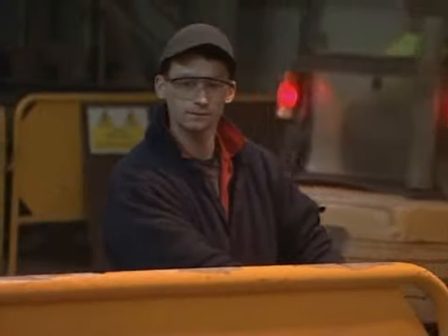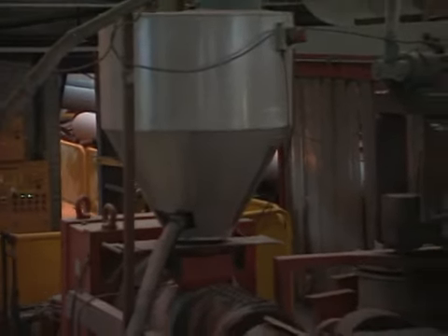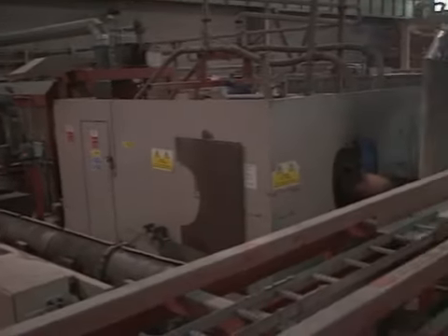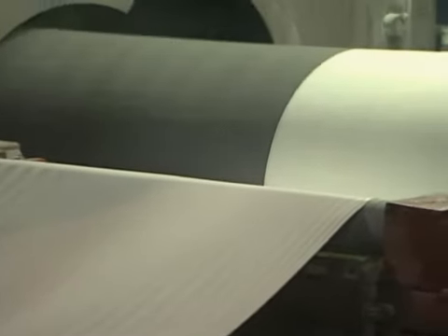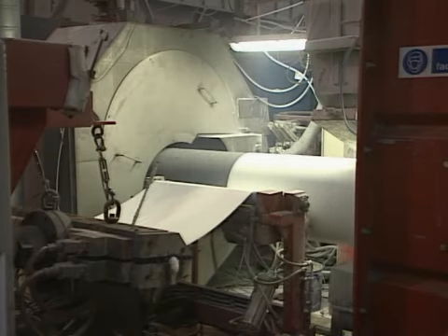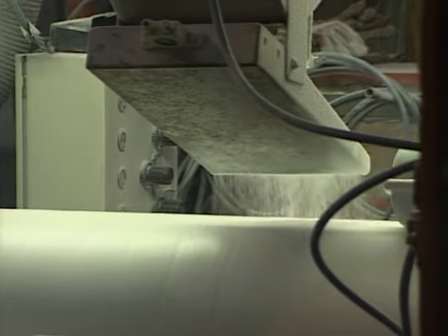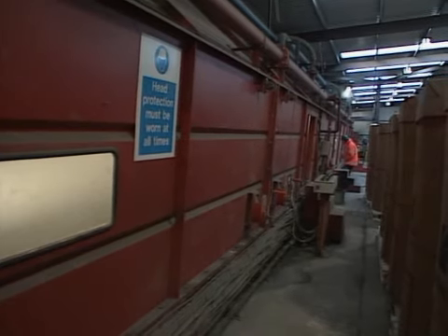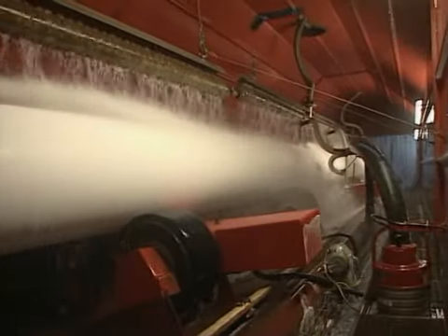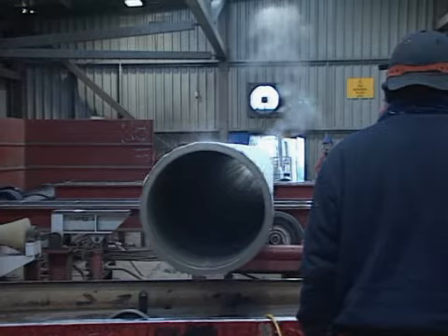Before the actual coating is applied, the pipe is preheated using induction coils. Using several coating stations positioned closely together, a 3-layer coating system is applied on the pipe. The top layer of polypropylene is wrapped around the pipe in an almost molten state. For safety reasons during pipe storage and in order to ensure enough grip during pipe lay, the outer surface of the coating is again roughened using polypropylene particles which will partly melt into the coating. The pipe is cooled using water. Now the actual coating operation is finished.